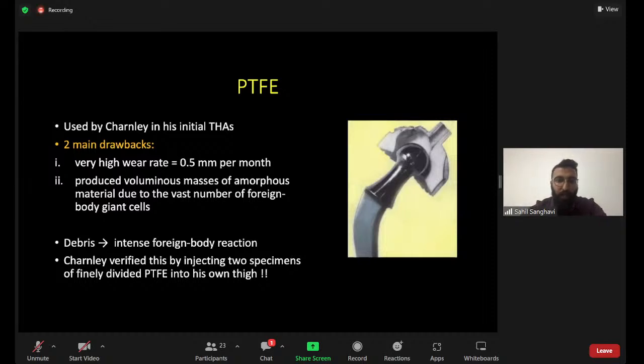It had a very high wear rate, almost 0.5 mm per month. In addition to this, it produced voluminous masses of amorphous material, which again caused foreign body giant cell reactions. So the debris of this PTFE material caused intense foreign body reaction, and this was even verified by Sir John Charnley, who injected 2 specimens of PTFE into his own thigh and found the reaction to be there.